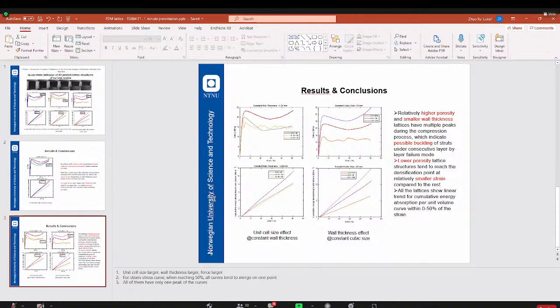But I think this is a good question, especially for the scale effect, for the categories where we have the same porosities but different unit cell size and cubic size. In general, conventional manufacturing techniques tend to have fewer defects compared to 3D printing, because for 3D printing, especially with the FDM printer, there is an effect from the first layer, and also other factors like temperature distribution on the build plate and other parameters. So this will affect the internal defects of the structures. So when you have different scales, you will have different results.